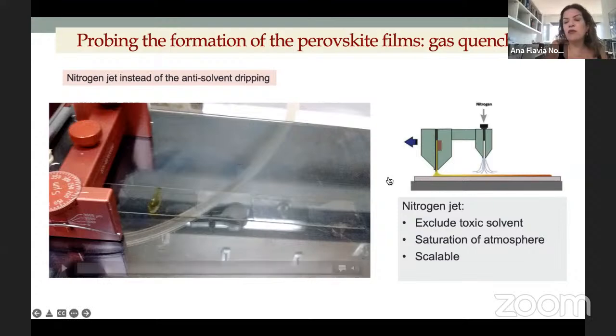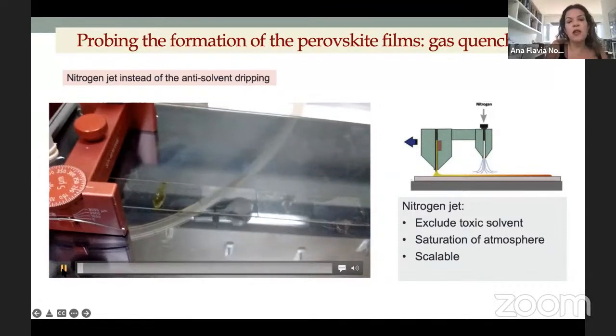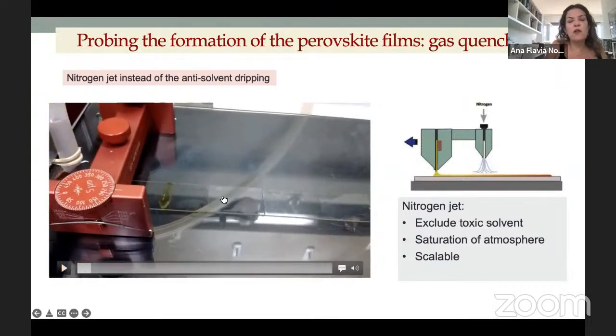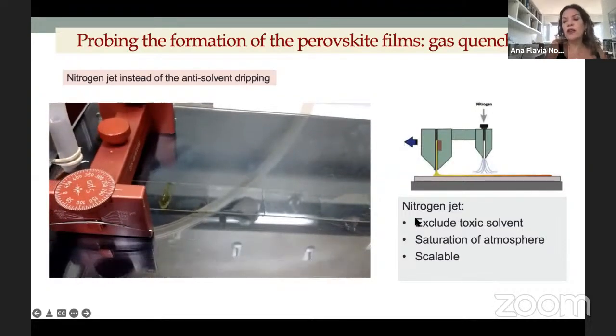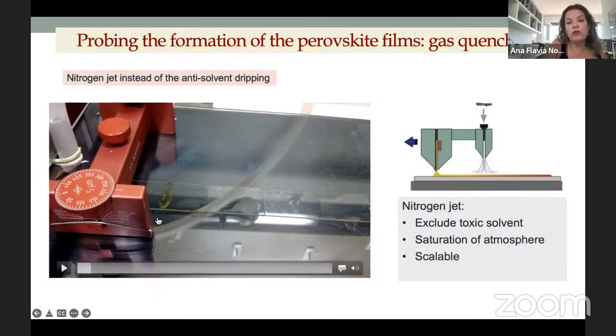And also, instead of the spin coater, you can use, in our case, let's see if I can play this video here. It's not working. I'll try to pass. So this is what we call a blade coater. So what's interesting about this method here? We can exclude toxic solvents because we are using nitrogen to form the perovskite. We avoid the saturation of the atmosphere of our glove box, and it's scalable if you really think about large area depositions. So basically, this is the precursor solution.